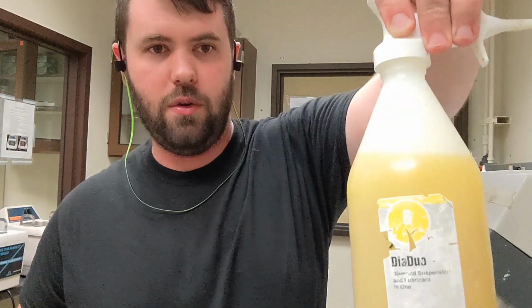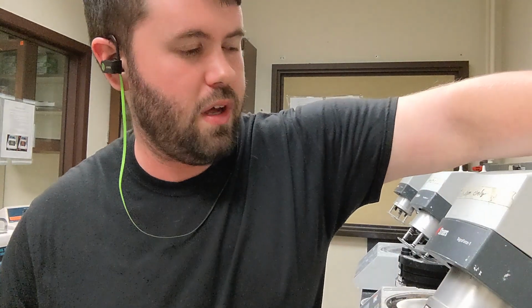All right, so after our rough grinding, I believe is how it's listed in the handout, our final step is polishing. So polishing is basically just continued grinding, except instead of using sandpaper pads, which have silicon carbide particles embedded in them, which are very, very hard and used to remove material, we are now moving to these 3 machines, and they use cloth pads, and instead of having the abrasive particle in the pad itself, we are adding a liquid to the pad, this stuff, this little green or yellow goo, kind of looks like milk, yellow milk, I guess, and inside that liquid are diamond particles, so pure carbon, very, very tiny diamond particles.